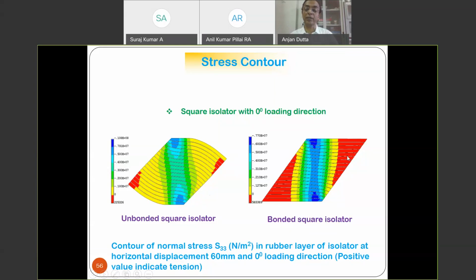And one more important thing which is happening, look at the one which is fully connected to the substructure and superstructure. This red zone is actually a tension zone. So tension zone, when you compare this with the unconnected one, tension zone is much lesser. So what will happen in the process? The amount of tension developed, even the tension value, is lower. So there's a possibility of delamination, because tension is the one which is responsible for delamination of FRP from the elastomer layer. So tension is much lesser. So they are much more stable compared to the one which is connected.